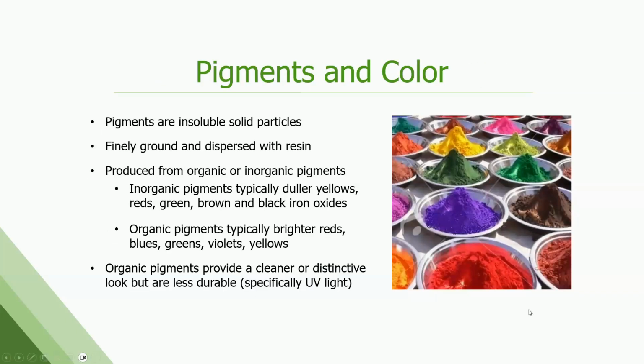So pigments, this is the fun part. This is how great it looks. These are insoluble particles. They're finely ground to a really small level and then dispersed within the resin or the polymer. And that needs to happen evenly so you get a nice even color. We use organic and inorganic pigments both. Inorganic pigments are metal oxides, usually things that are mined out of the ground. They're then fired at high temperature to make them very, very stable. They tend to be your earth tones, a little bit duller yellows, reds, greens, browns, and blacks.